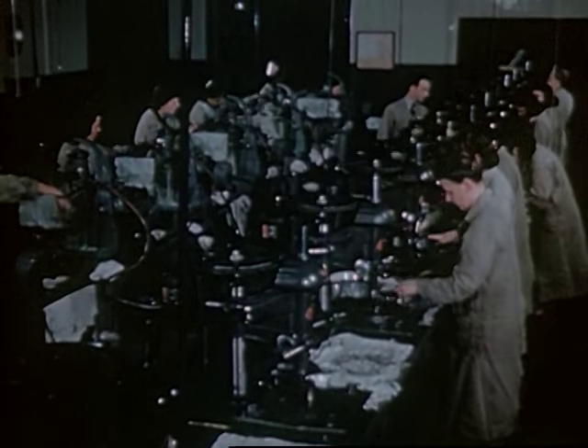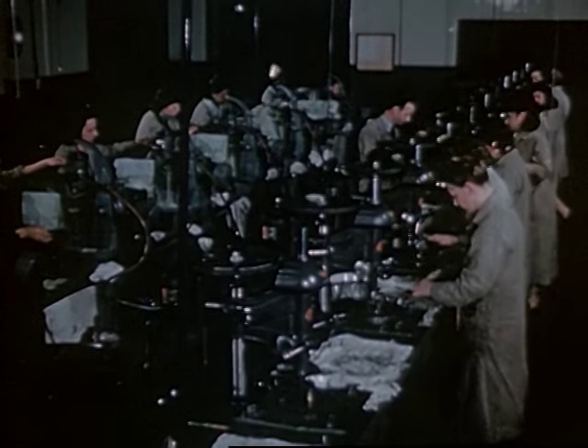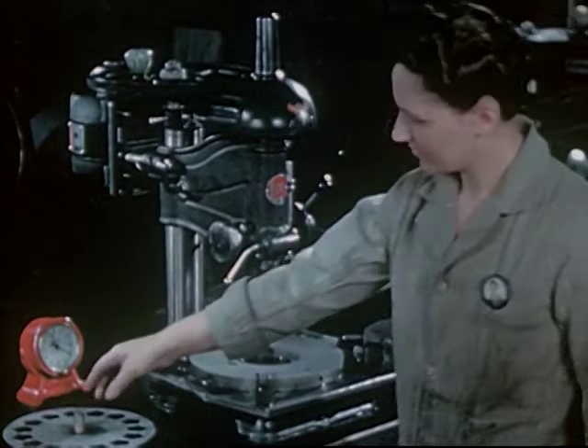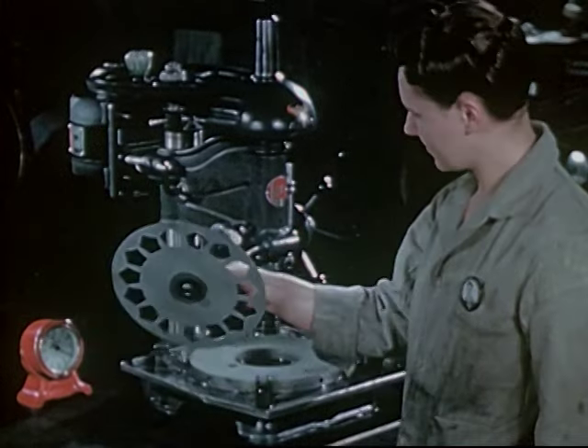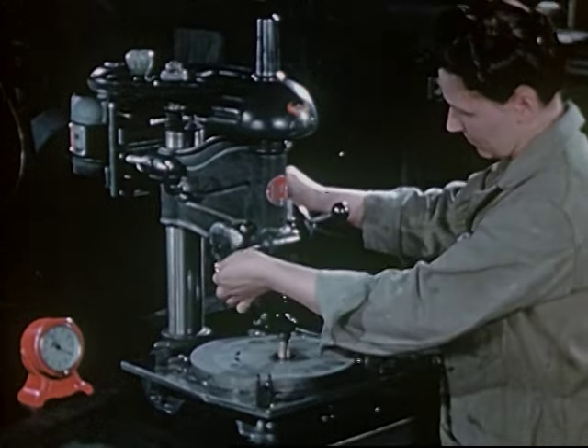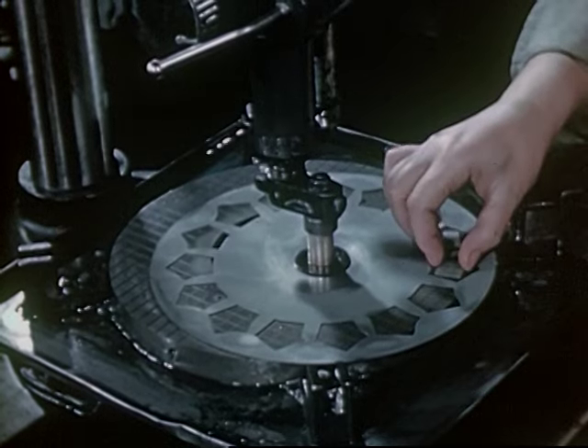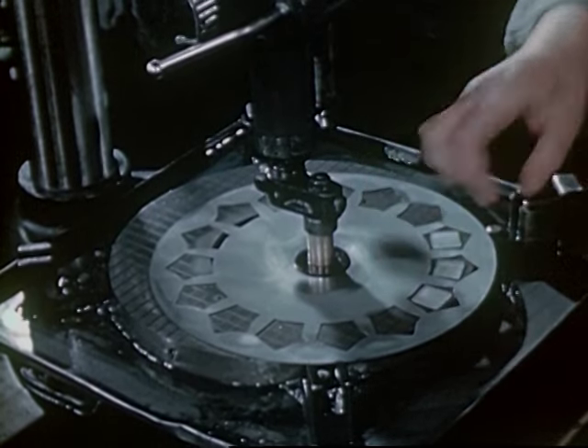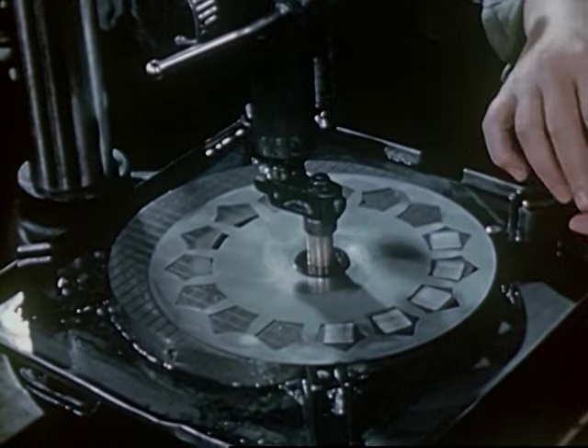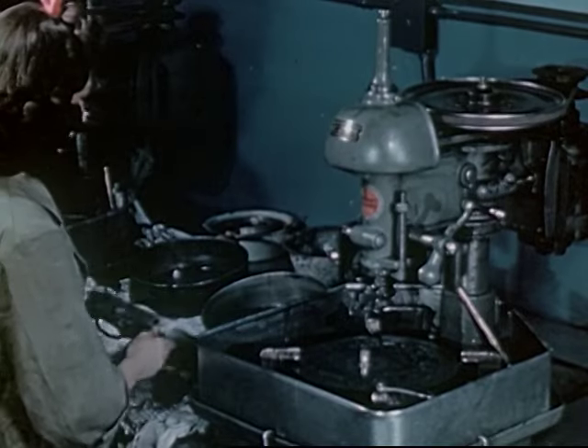In the first lapping machines, coarse blanks are ground down to a thickness of approximately 17 thousandths of an inch. The lapping machines are flat cast iron discs grooved on the surface. On the bottom disc is placed a thin zinc holder with pentagonal openings. When this holder is secured in position, the rough blanks are inserted in the openings. The top grinding disc, which is also grooved, is now placed carefully on the blanks.